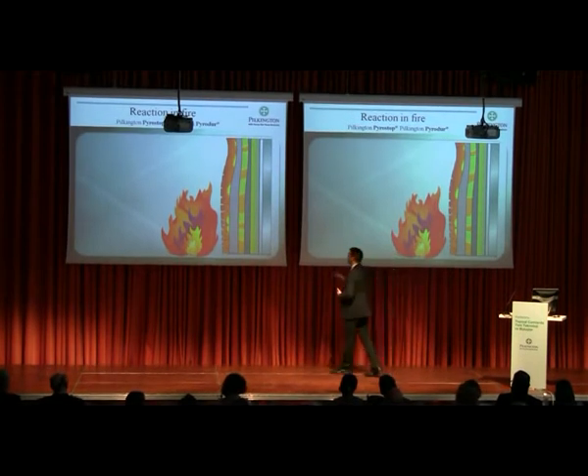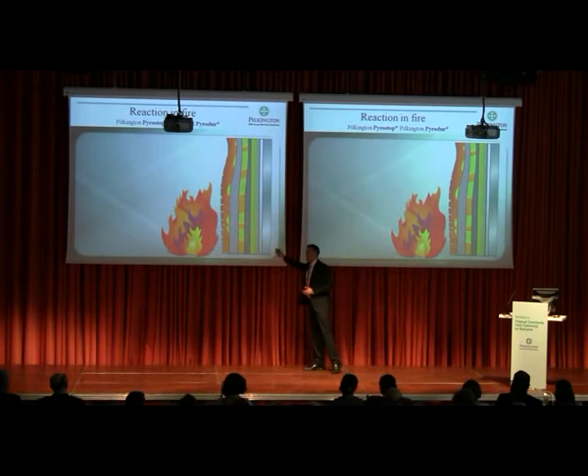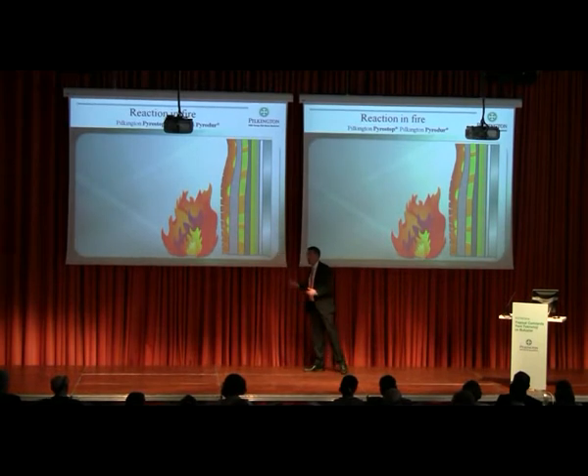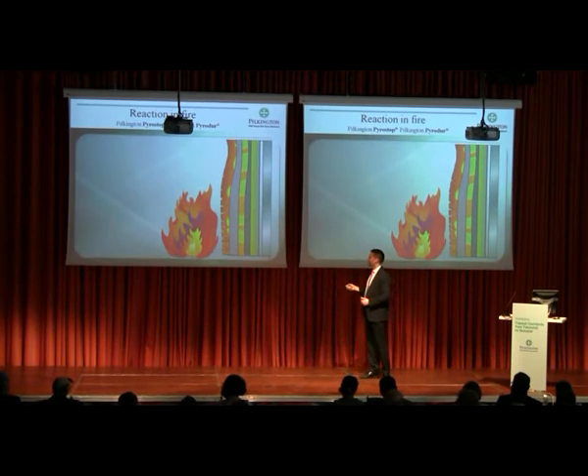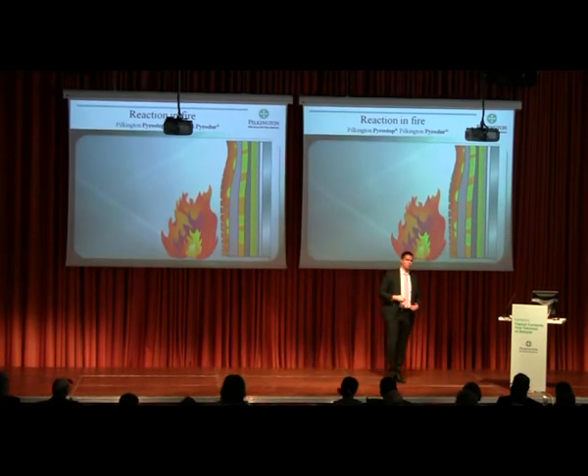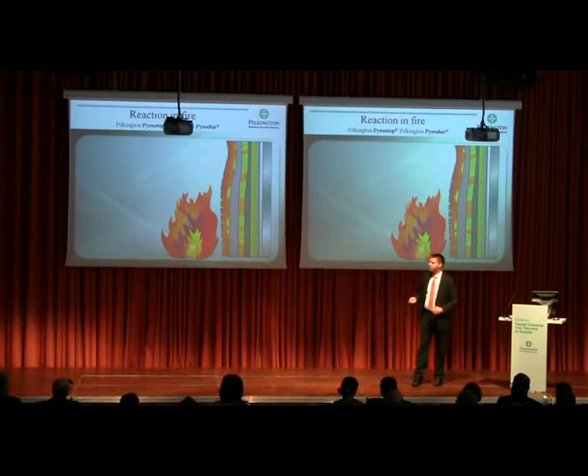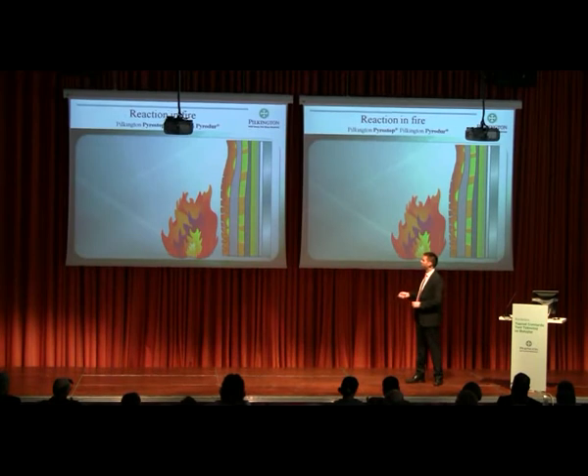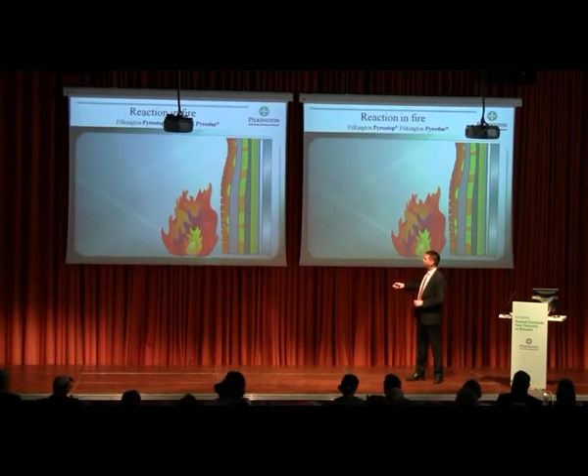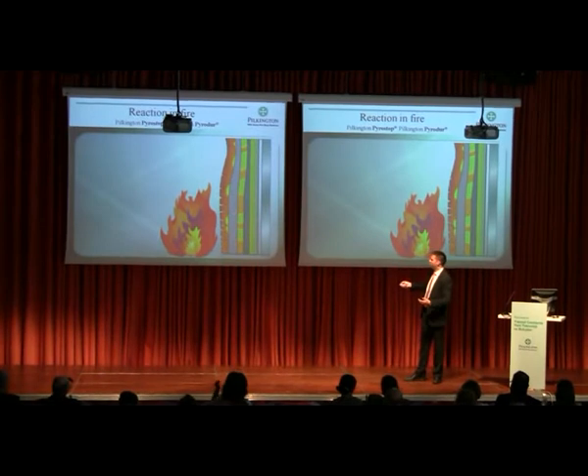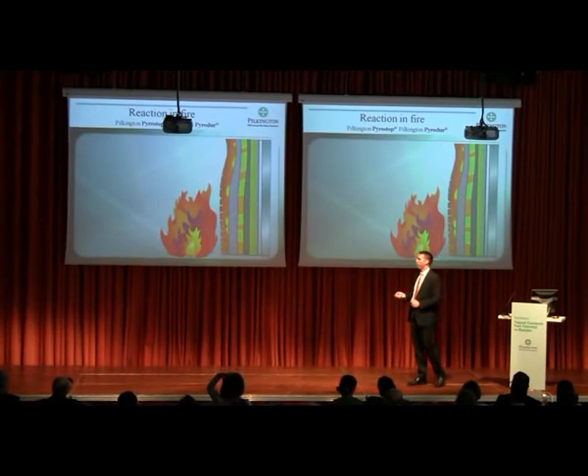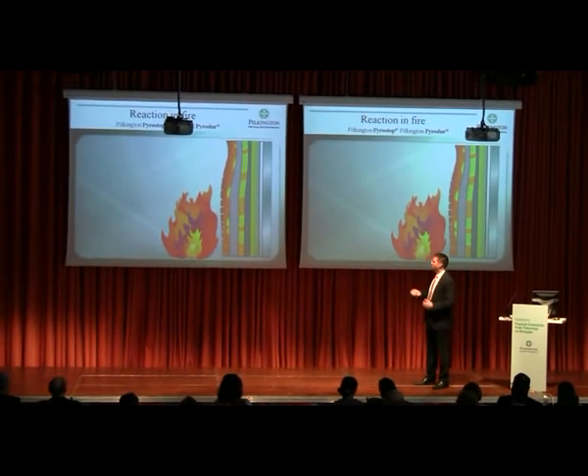The surface temperatures we are measuring on this side, after the required time, are about 100 to 120 degrees. On this side we have almost 1000 degrees. So there's really a huge difference if you're using an insulated product like that one. The interlayers are foaming up step by step after 30, 60, 90 minutes, whatever we need.